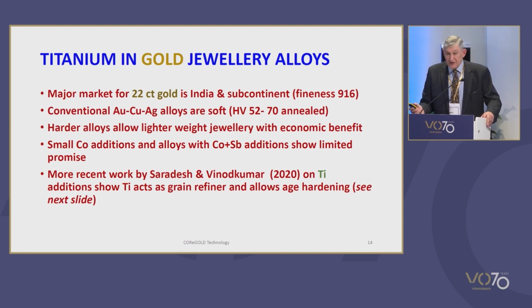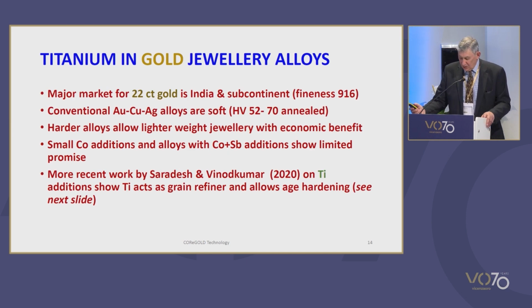A major market for gold jewellery is 22 carat gold in the Indian subcontinent. With a fineness of 916, such 22 carat gold alloys are soft, with hardnesses of about 52 to 70 Vickers in the annealed condition. Use of a much harder 22 carat gold alloy would allow lighter weight jewellery with economic benefit. The use of small cobalt additions and conventional alloying with cobalt plus antimony additions show some promise.